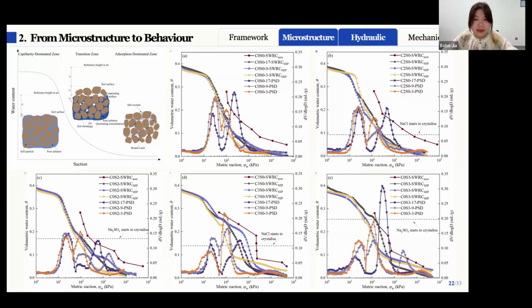And by linking these processes to the SWRC, we observe that the dominant pore size corresponds well to the transition zones of the retention curve, as they represent more storage space for water. This indicates that capillary water content is largely controlled by the spatial distribution of the dominant pore network. And when macropores dominate, that strongly influences the overall water retention behavior. In contrast, micropores contribute less to the total water content, which is reflected in the relatively gentle slope of the corresponding segments of the SWRC.